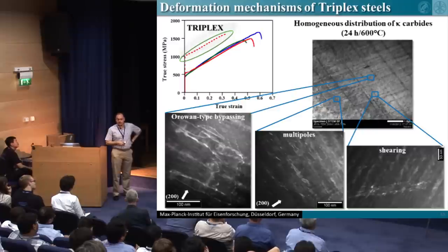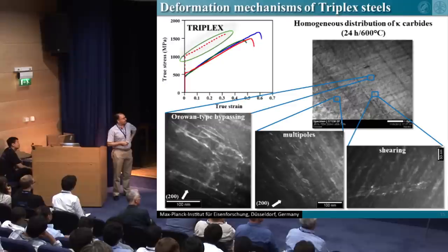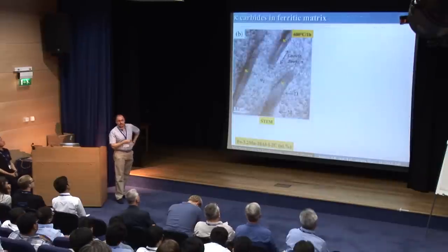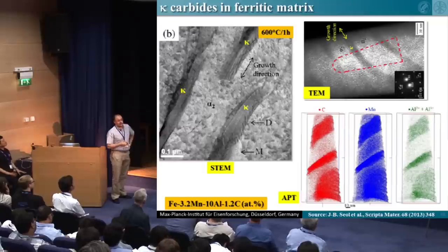So as you can see, understanding the role of the particles in the strain hardening for this system is much more complex because we have different areas, we have different dislocation density in terms of dislocation patterns, and this is much more challenging. So just to conclude, as I said before, what happens in a ferritic matrix? This is a recent work from one of our colleagues, and you can immediately see that the morphology is completely different. So kappa carbides, the interfaces are semi-coherent, incoherent.